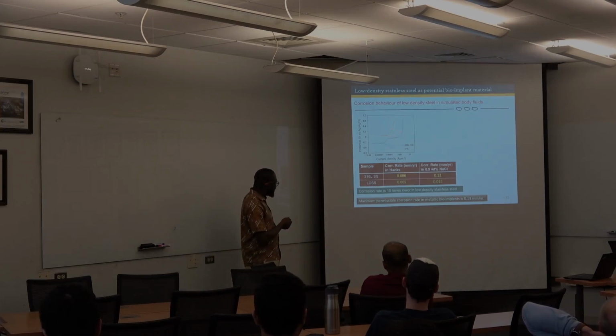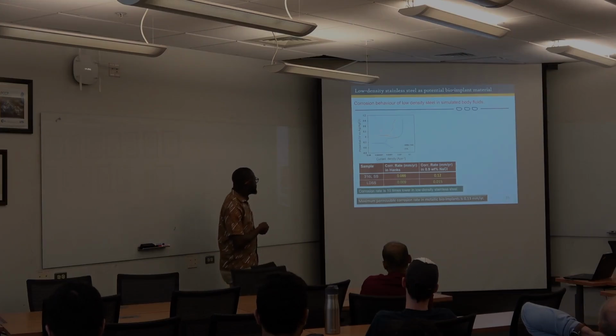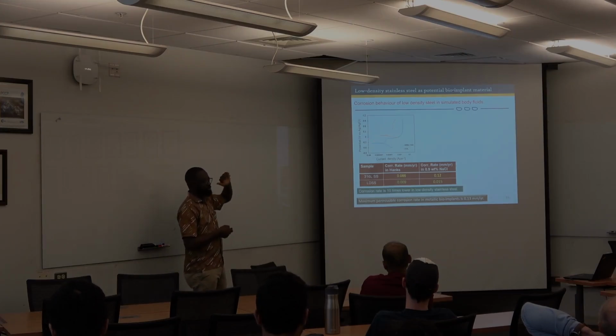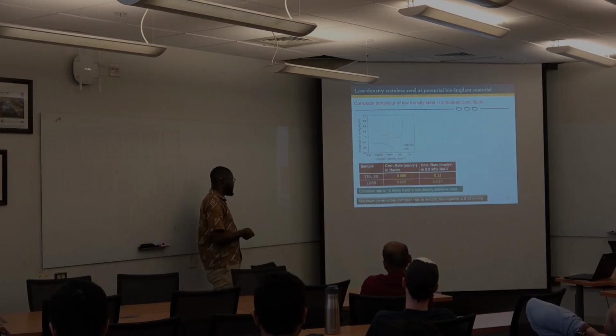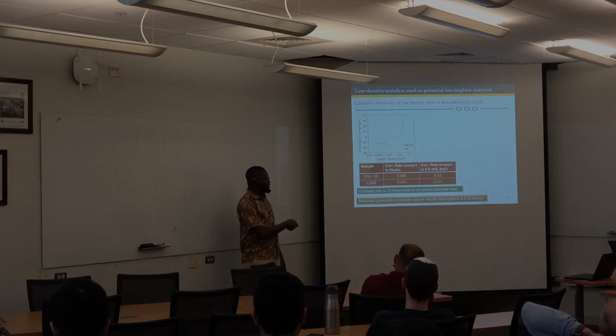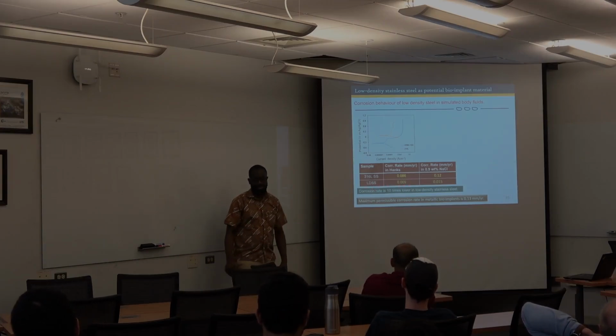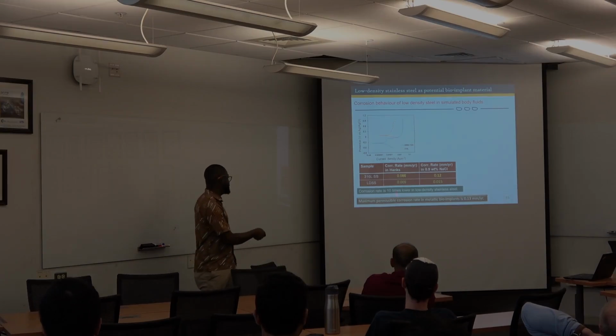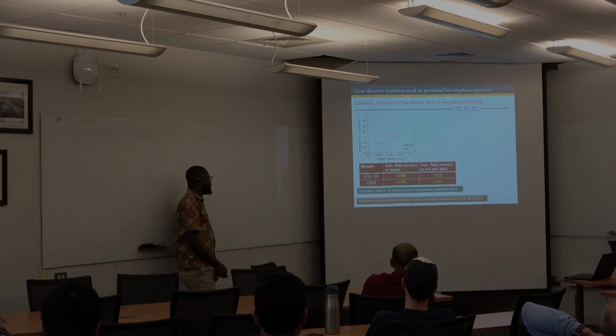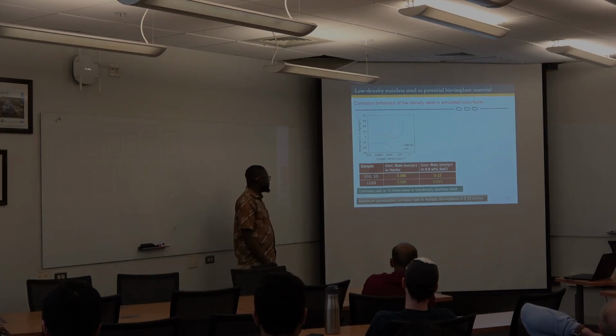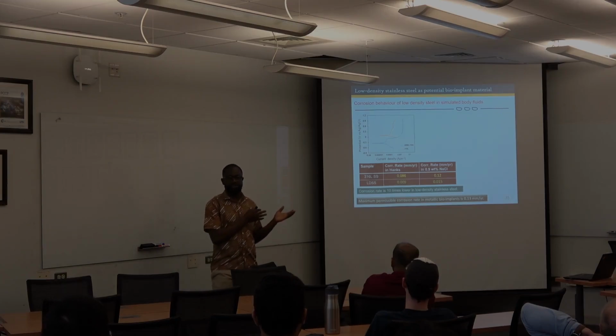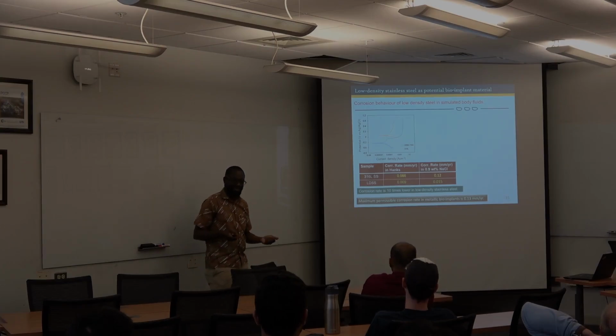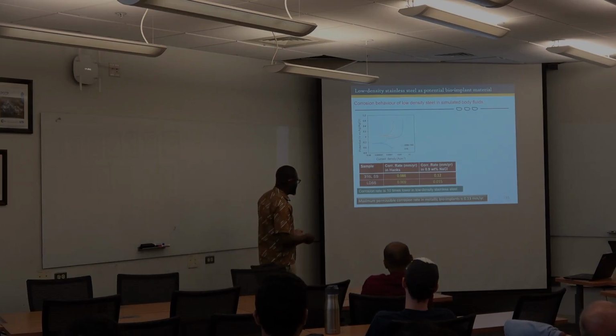You can see this is a commercial grade 316 system. In terms of the corrosion potential, thermodynamically, it's not likely to corrode. Okay, but in terms of kinetics, when it starts corroding, the low density stainless steel is even 10 times slower. Okay, and this is in 0.9% NaCl. So the question is, why is 3 to 5% of chromium added to this grade of steel more effective than when you have 18% of chromium? So these are the questions that I've got here basically.